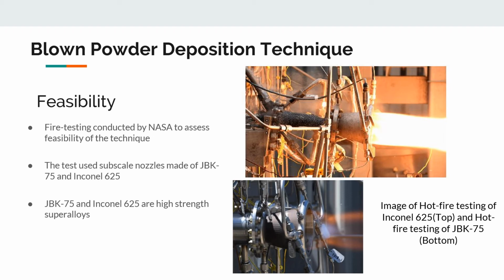NASA conducted tests on subscale nozzles fabricated using blown powder deposition technology to further understand and implement the technology for full-scale channel wall nozzle fabrication. The test used subscale nozzles made of Inconel 625, which is seen on the top image, and JBK75, which is seen on the bottom image. Both JBK75 and Inconel 625 are high-strength superalloys suitable for such applications.